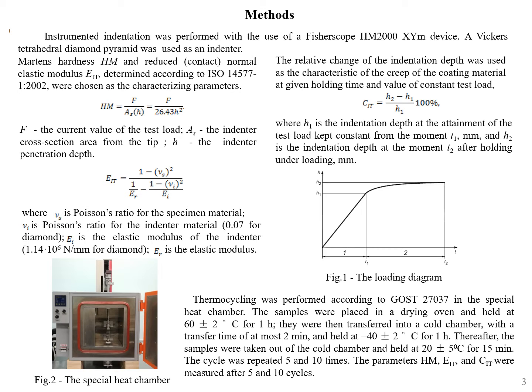Thermocycling was performed in the special heat chamber. The samples were placed in a drying oven and held at 60 centigrade for 1 hour. They were then transferred into a cold chamber with a transfer time of at most 2 minutes, and held at minus 40 centigrade for 1 hour. Thereafter, the samples were taken out of the cold chamber and held at 20 centigrade for 15 minutes. This cycle was repeated 5 and 10 times.